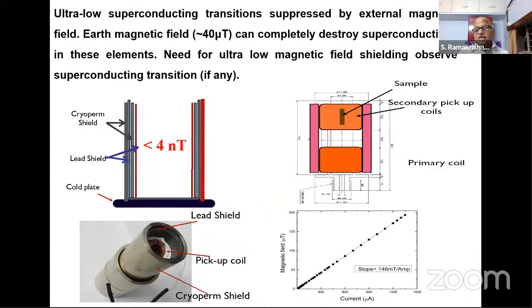So it turns out that as you go lower and lower in superconducting transition temperature, you need to shield it from the Earth's magnetic field, because Earth's magnetic field is 40 to 45 microtesla, and that is good enough to kill the superconductivity. Even if you cool down to 1 microkelvin, if you don't shield the system, you are not going to see it. So the second task for us is to shield the Earth's magnetic field.